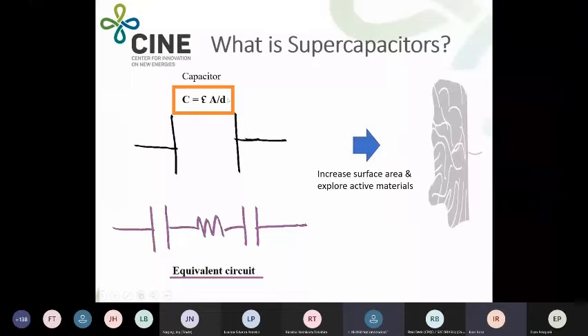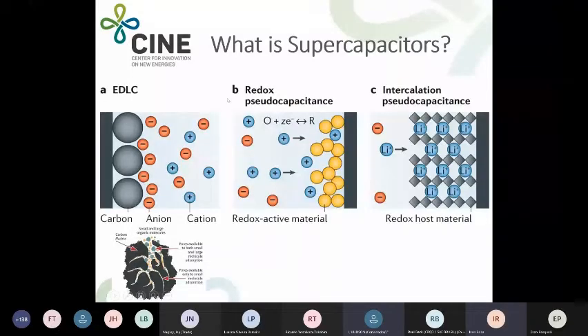D is related to distance, by adsorbing ions on the surface of this ultra high surface area material. And so we reduce this parallel distance between the electrodes to nanometer size. So basically, a supercapacitor works like this. We adsorb ions on the surface of the material, and we have what we call an electric double layer capacitor, which charges in a few seconds. But we also want to increase the energy inside a supercapacitor, and in order to do that, we use two tricks. We combine this carbon-based material with metal oxides to have an ultra-fast redox reaction on the surface of the material. And we also try to play with a very interesting material that allows an ultra-fast intercalation process.